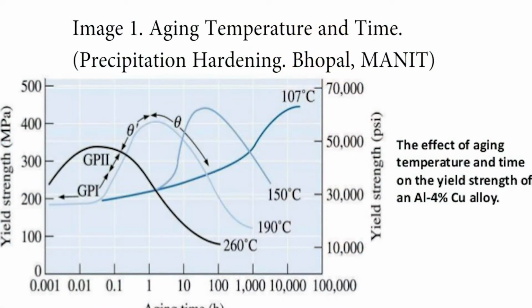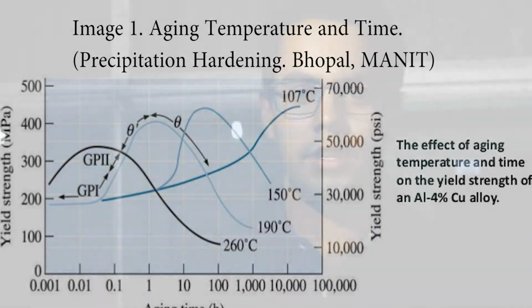Precipitation hardening is used because the strength and the hardness of some metal alloys may be enhanced by the formation of extremely small uniformly dispersed particles of a second phase within the original phase matrix. This is accomplished by appropriate heat treatments. This heat treatment is called precipitation hardening because of the small particles of the new phase that are named precipitates.